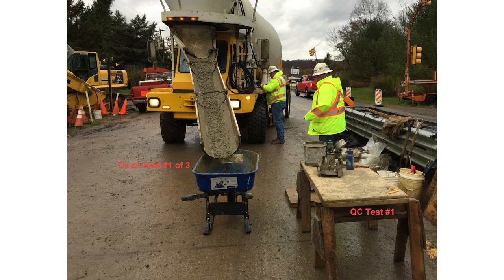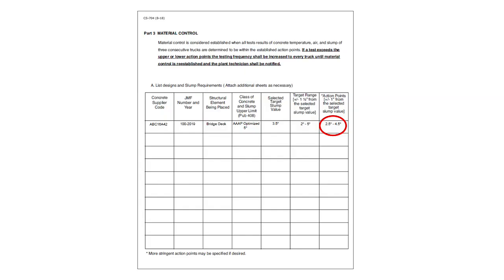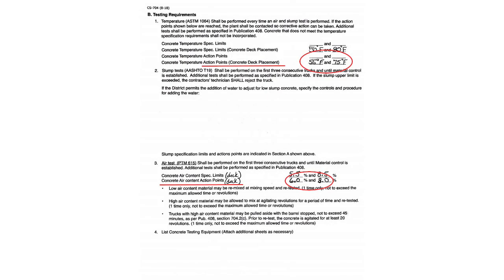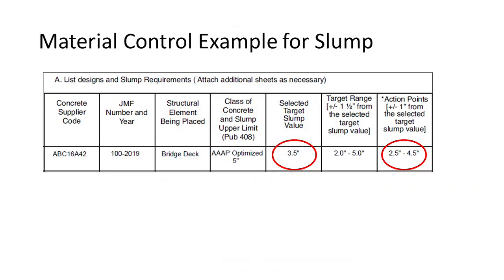Quality control, or QC testing, is required on the first 3 consecutive concrete delivery loads for material control, regardless of the method for placement. Material control is considered established when the test results of the first 3 loads are within established action points for air content, slump, and temperature. Once this is established, the frequency of testing may be reduced to a minimum of 1 quality control test per 50 cubic yards. Material control example for slump.